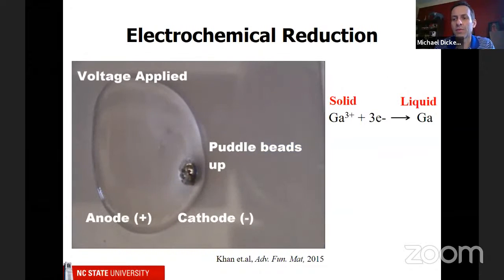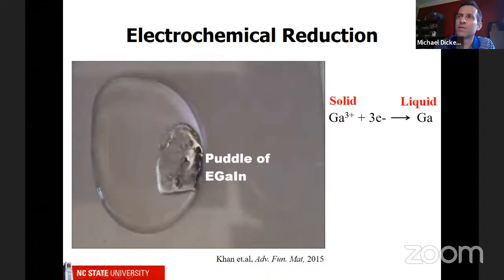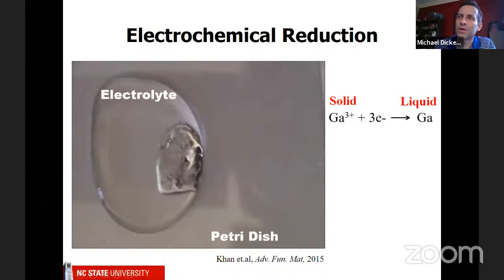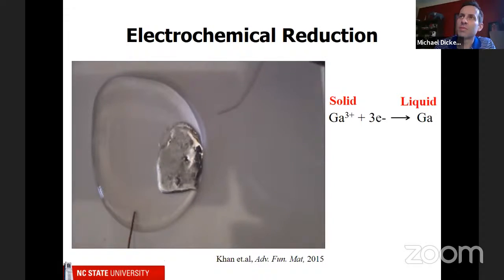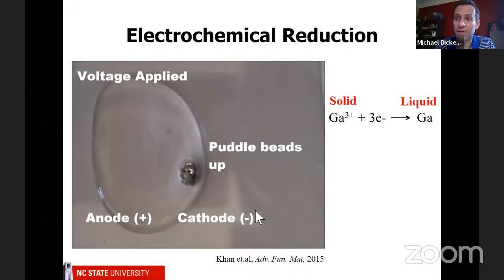And you'll see that we can remove the oxide layer and the metal will bead up due to surface tension. Now, I want to point out one thing at the very end of this video. If you look at the very end of the video, you'll see that when the metal beads up, it looks like smoke, like right over here, but that's actually hydrogen bubbles. So once you reduce the oxide layer, the metal can react with the water and it can form bubbles.